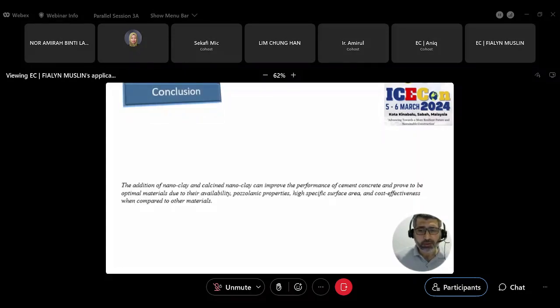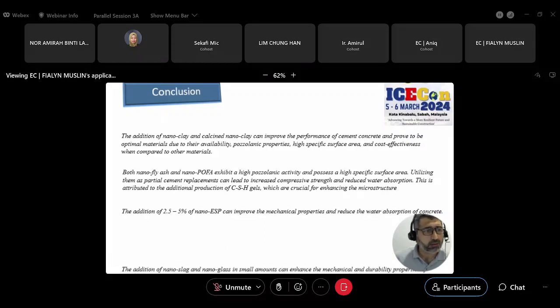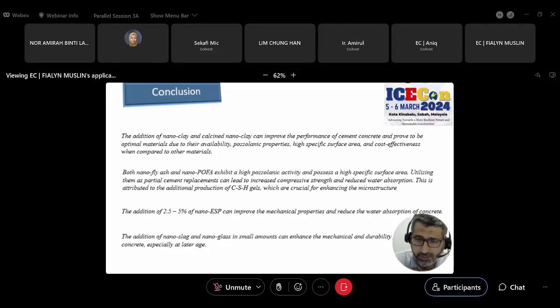So as a general conclusion of these, I don't need to increase the time. There are many other results to share, but I will just go over the main points of the conclusion of these studies. One of them is that the addition of nanoclay and calcined nanoclay can improve the performance of cement concrete and prove to be optimal materials due to their availability, pozzolanic properties, high specific surface area, and cost effectiveness when compared to other materials. Both nano fly ash and nano POFA exhibit a high pozzolanic activity and possess a high specific surface area. Thus, utilizing them as partial cement replacement can lead to increased compressive strength and reduced water absorption.